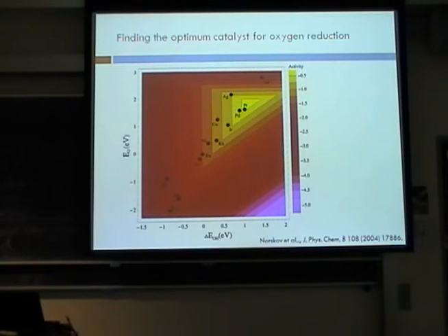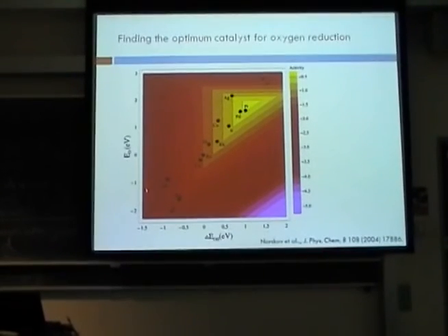Right, so the reaction won't be able to go because the surface is already crowded with adsorbates that are too happy being there. And you'll see that most of the pure metals fit that description, that they're binding things. Negative means stronger adsorption energies. They're binding the intermediates too strongly, and so the surface is just getting self-poisoned with all the intermediates from oxygen reduction. Right, if we're over here with, say, gold and to a lesser extent silver, then the intermediates are bound too weakly, so they never really want to form on the surface, and so you can't get the reaction to occur.